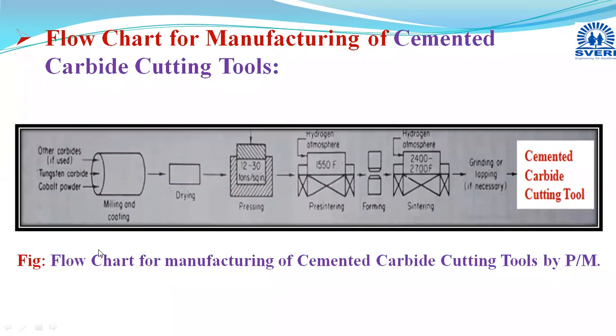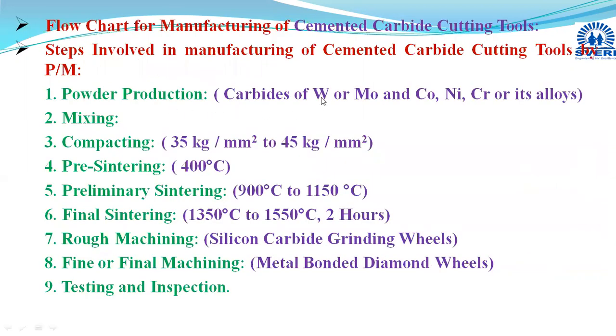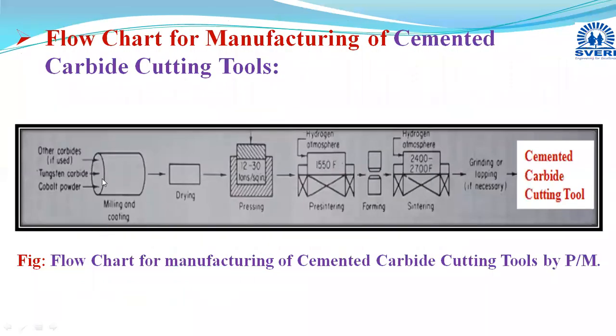It may be tungsten carbide or molybdenum carbide. Okay, and these components, especially the carbides of tungsten or molybdenum, then the cobalt powder, nickel powder, chromium powder, all these are manufactured by the chemical process known as the reduction method, reduction of their respective oxides with the help of carbon or hydrogen. These powder particles are obtained and can be easily converted to their respective carbides, and those powder particles are used. Then their uniform and homogeneous mixture is obtained in the mixing stage, which is also termed milling.